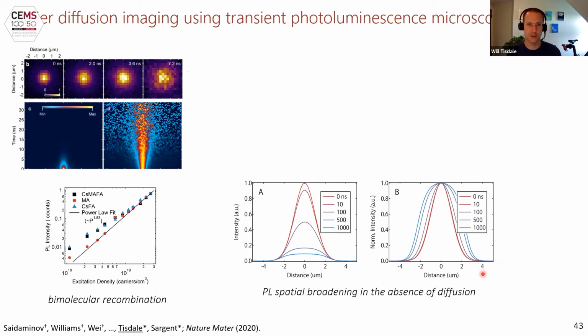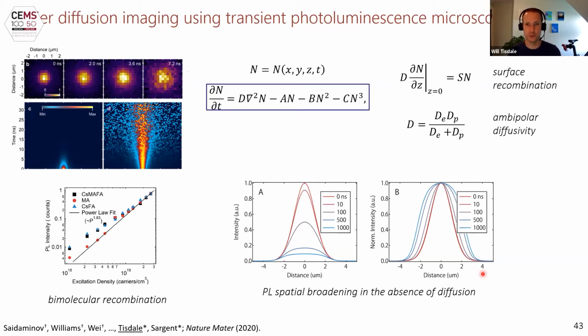So to accurately model this data, to analyze it, you need to solve the full partial differential equation in 3 dimensions, where we're modeling the carrier distribution in 3 spatial dimensions and time. It's a simple transport relationship, just like you learn in undergraduate chemical engineering, just applied to charge carriers in a solid. These reaction terms refer to different linear and nonlinear charge carrier recombination mechanisms. We include a boundary condition at the surface that accounts for some surface recombination. And it's important to note here that we're not independently measuring electron and hole populations. We don't know which carrier is doing most of the diffusing. What we are measuring is an effective ambipolar diffusivity and the product of the local electron hole pair density.